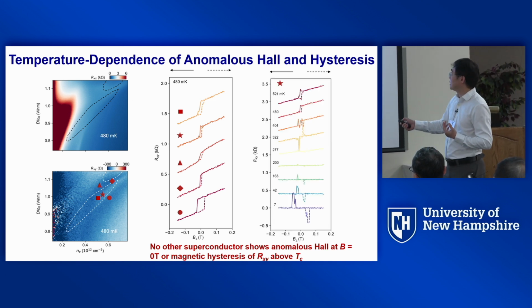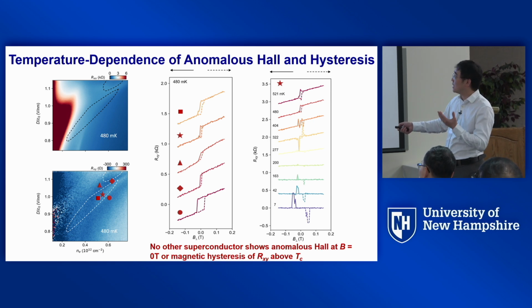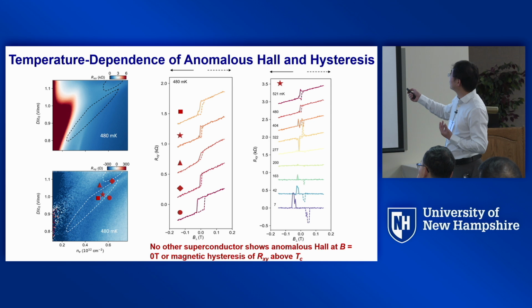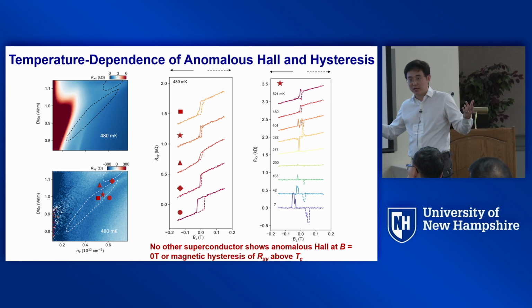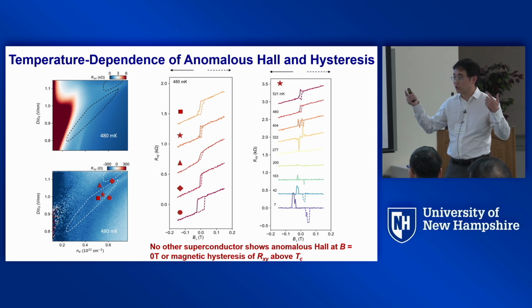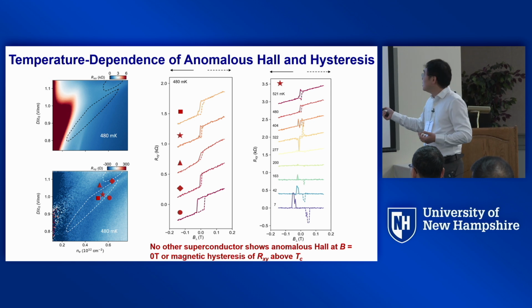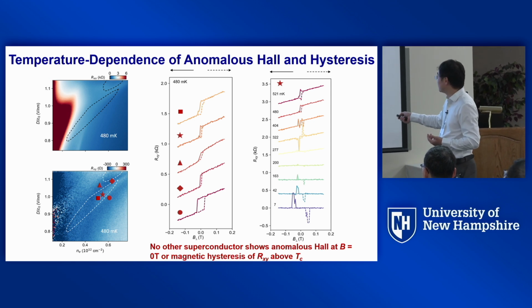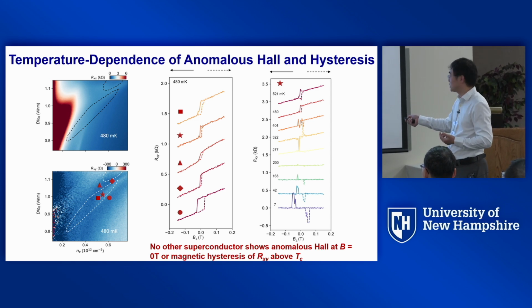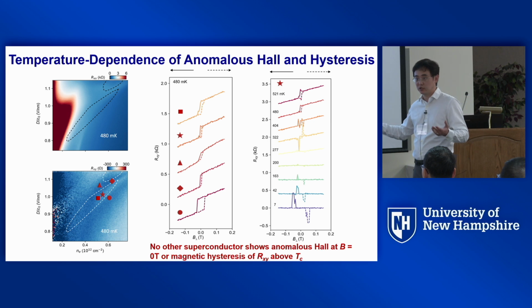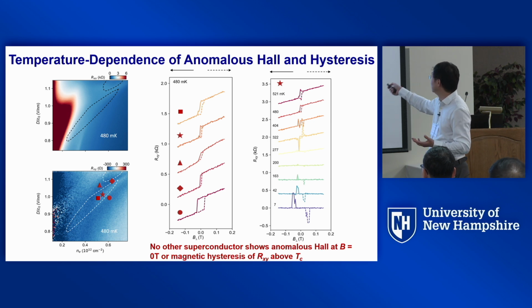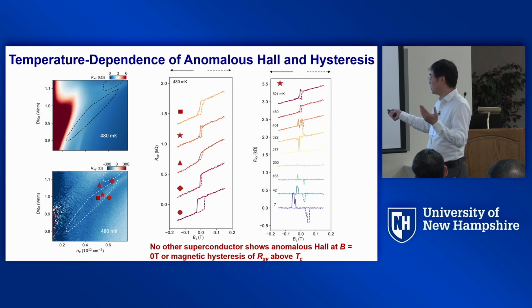And you can watch as a function of time. For example, you stay at the star position, which is inside the SC1 region, and you cool it down. You see above TC, you got a magnetic hysteresis in Rxy. As you cool down, once you get into the superconducting state, you just measure a 0 Rxy. It gets shorted. But you still have this hysteresis with the field back and forth, just like the one you see in the Rxx channel. Although the background, normal Hall and anomalous Hall signal are both 0.